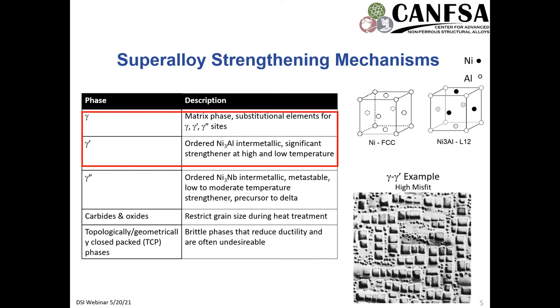And on the bottom right, we do have one of the micrographs that you may be quite familiar with just in general for superalloys. This is a gamma gamma prime example, and this is showing a high lattice parameter misfit, and that lattice parameter misfit is really the effect that the substitution and the ordering has on the spacing between the atoms. And so if you have an orientation relationship or a coherent secondary gamma prime that's existing within the material, you have a level of misfit that provides strength to the material through an elastic strain in the material, or you can have loss of coherency once it reaches a certain size or temperature exposure or deformation throughout the surface or processing conditions.